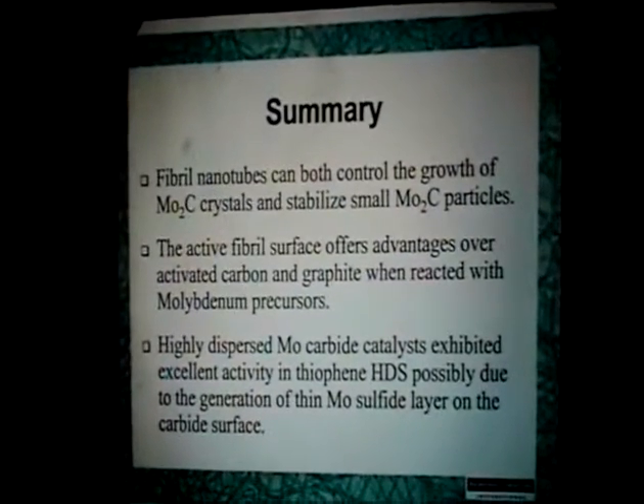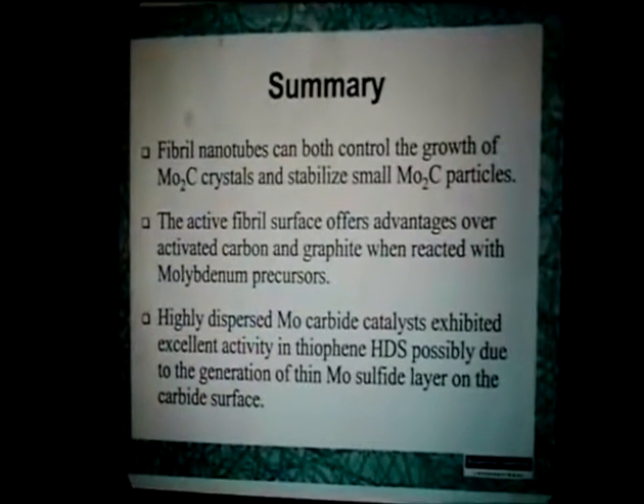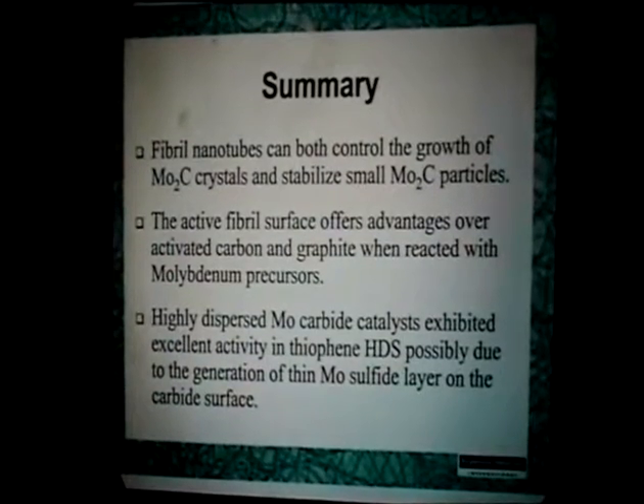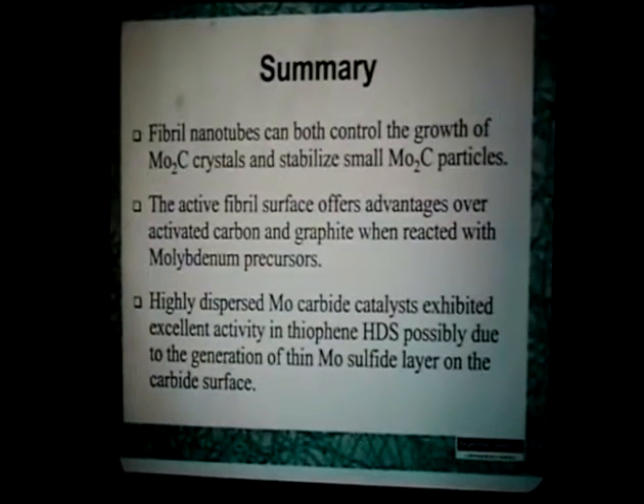The fibril nanotubes can control the growth of molybdenum carbide crystals and can stabilize those very small particles. It offers advantages over activated carbon and graphite, mainly because this is a very well-defined material, well understood, pretty uniform. And these highly dispersed molybdenum carbides have a comparable activity to the literature for HDS. And this is due to the formation of this thin skin of molybdenum sulfide on the carbide surface.